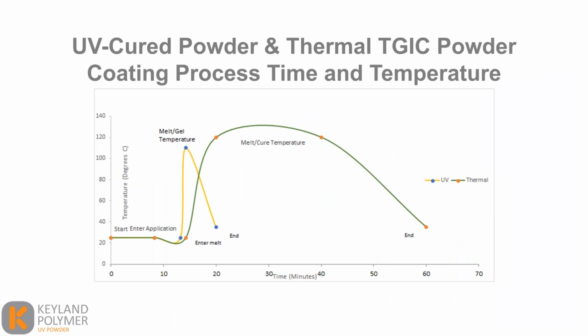So comparing this from a time and temperature standpoint, the yellow line is your UV curable powder coating system, and your green line is your thermoset system. The temperature of the coating only reaches 110 degrees C. At that point, it is sufficiently melted and flowed. Whereas for a thermoset system, it has to reach 120 degrees C, and it needs to sustain that for 20 whole minutes, which is the duration of the application, melt, and cure of a UV system. The total time for a thermoset system in this simulation is 60 minutes.